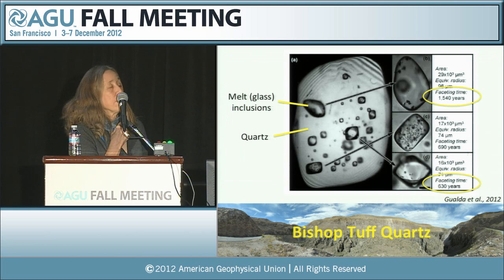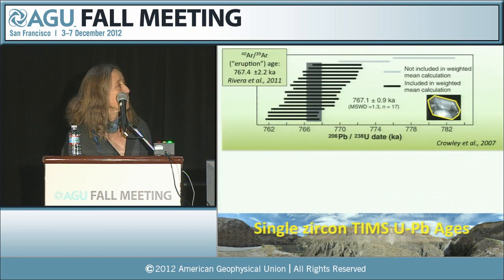They also use the rates of faceting of melt inclusions within quartz. So here's a melt inclusion in a quartz crystal. We imagine that when the melts are entrapped initially and then ultimately freeze as glass, they have a regular shape such as this, but that over time they become faceted such as this. And they've estimated the timescales that are required to go from this more amorphous shape to a faceted shape. And again, for the Bishop Tuff quartz, 1,500 years here, 600 years here. So we're looking at timescales of several hundred years to a few thousand years for formation of these crystals.